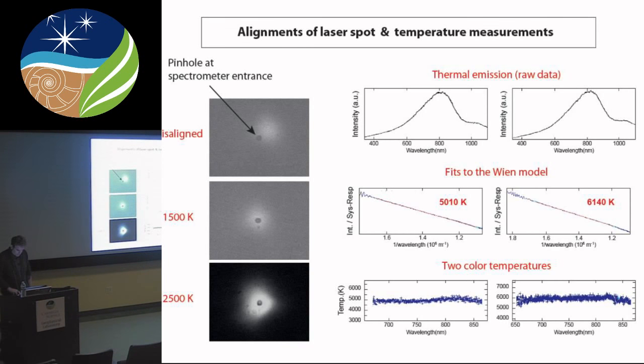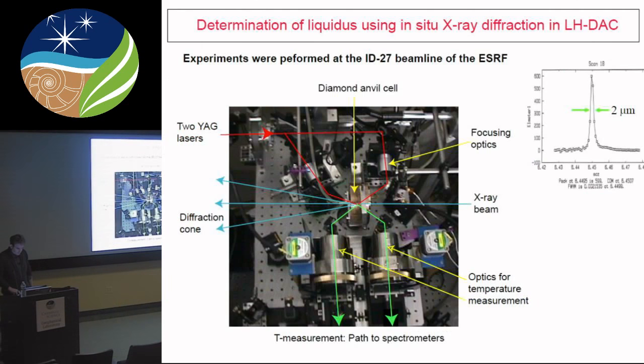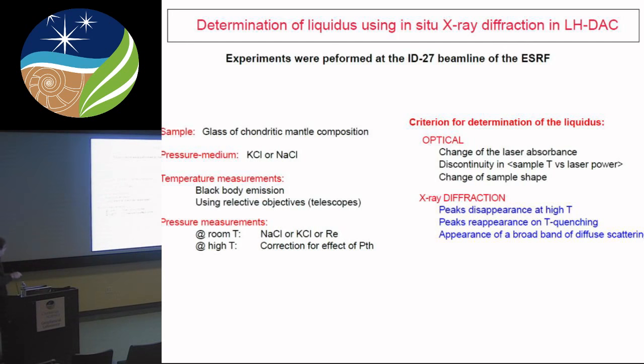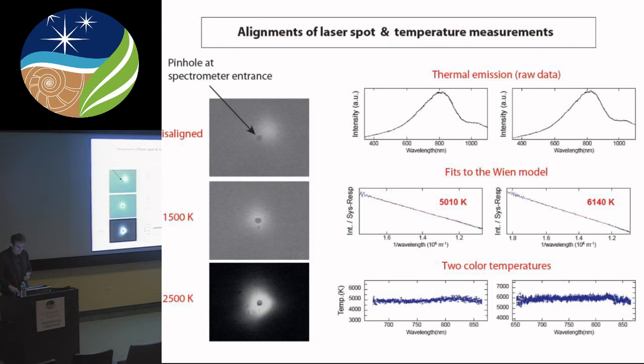Everyone knows now, if we want to go into the details, of course, that there are some more difficulties to measure the pressure, because if you don't want to mix calibrant with your sample, we know the sample pressure increases when you do the laser heating, but you can correct this effect by calculating some thermal pressure. But it makes an error on the final pressure at high temperature.